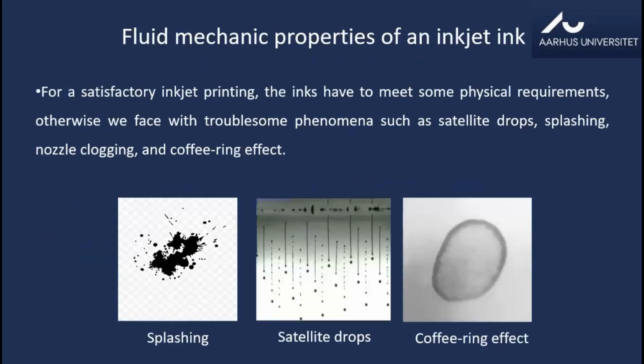Now, as I said earlier, the heart of any printing process is that it has to have the right property of the functional ink. If your ink is not right, trust me, nothing will work no matter how great your printer is. So both have to be compatible. The rheological properties of the inks are very important. It should be a very well dispersed solution. Your ink should not settle down. If I make the ink solution and after 2 minutes everything settles down, that's not going to work, because the moment you want to print it, after 1 hour, everything would have agglomerated, precipitated, and nothing is going to come out.